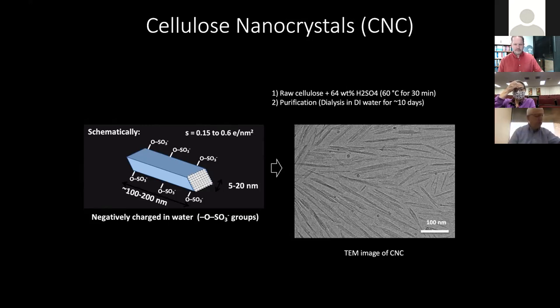And then what you have to do at the end, especially because you have all this acid, we generally use tenfold dilution with water to interrupt the reaction, so to make sure that we can control it well. And we also do this in an ice bath, so that we can quench the reaction almost instantaneously, because we might have a problem of redeposition of this partially solubilized chain into the colloid, and then it's really difficult to take them apart. But it's a pretty harsh acid treatment.